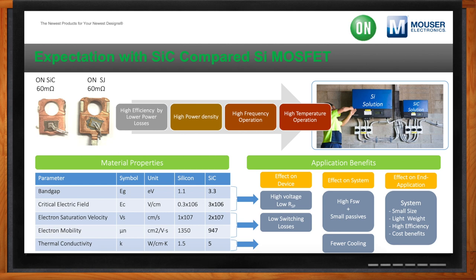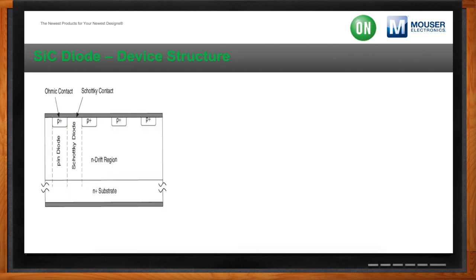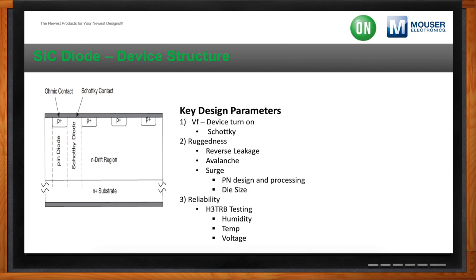Yeah, definitely. So the picture on the left is a simple silicon carbide diode, and it has a substrate, drift region, and then it has your contacts. But there's really three main parameters that we design around, and it's kind of trade-offs, but the key for us from a device manufacturing standpoint is to optimize all these three parameters, which is VF, which is the device turn-on, ruggedness, which is your leakage, how much does your device leak, as well as reliability. We do not want any failures in any system.